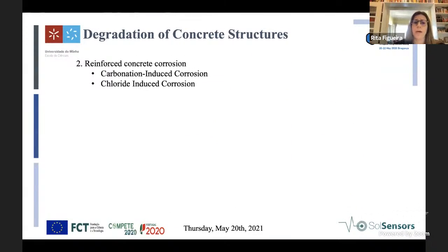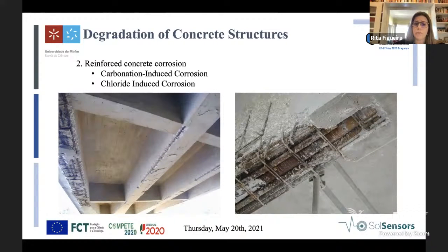So the degradation caused by reinforced concrete corrosion can be due to the carbonation of concrete, due to carbon dioxide presence, or due to the presence of chloride ions. You can see here cases of structures damaged by chloride ions. The main problem is that the rebar that is inside the concrete expands due to the formation of iron oxides, and due to that expansion, it leads to cracking of concrete. And after that, the concrete detaches, and you stay with the rebars completely exposed. This will lead to a consumption of the iron, which leads to a loss of section of steel, and in extreme cases, this can lead to the collapse of the structure.